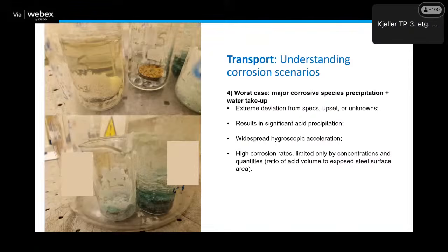And finally, some research in worst case scenarios. What if you get really icky stuff going into your pipeline? And as you can see, the colleagues at Corrosion don't even want to use their pressurized equipment for this sort of research. So it's just being done in glass beakers with a low CO2 pressure. And you can see that can have some very strong effects here. And again, it's mostly going to be limited by the amount of acid relative to the surface area of the steel of the system.